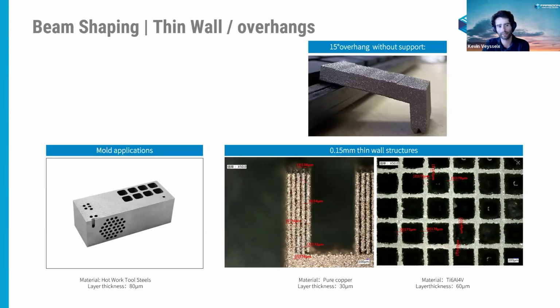So this was the part on the overhang. And so when we do beam shaping, we have to increase the beam a bit. Basically we make it 2 or 3 times bigger than the Gaussian beam. But it's not because we increase it that we cannot build thin walls. So here we have 2 applications. One, for example, is with pure copper, and here with titanium. Both have a wall thickness between 150 and 200 microns. So still with beam shaping, we can build really accurate thin walls. And that's really perfect in some tooling applications, but also in cooling applications.